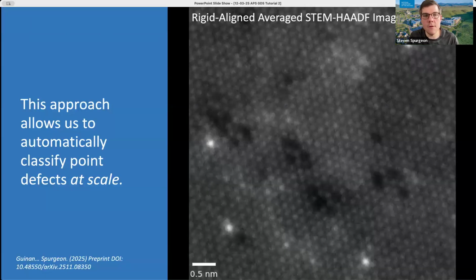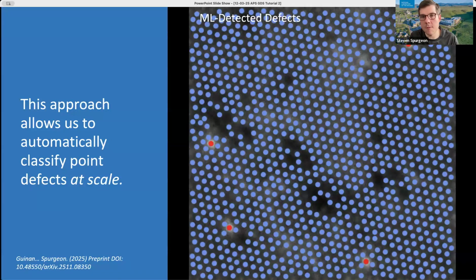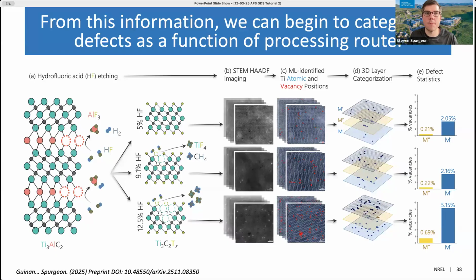So what this then allows us to do is to start classifying point defects at scale. We can go from these grayscale images to a distribution of atomic coordinates. We can identify where within the lattice that atoms are missing, where the adatoms are, and start to build up this ontology of what defects look like in the MXenes in a very statistical way.